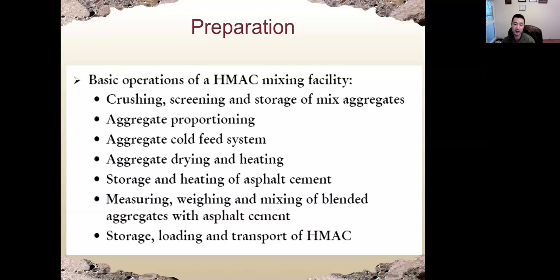And also the aggregate needs to be heated up. The temperature needs to be high because again, asphalt cement needs to be heated to reduce the viscosity so it can be mixed with the aggregate. Okay. And then the storage and heating of asphalt cement. Okay. And we measure weight and mix of the blended aggregate with asphalt cement. Okay. And also loading, transport, and paving asphalt concrete.